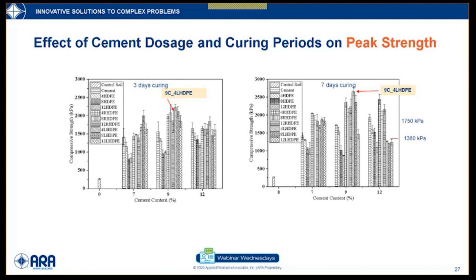This is to mention that these two red lines are indicating the minimum strength requirements according to the state and federal highway. It's showing that the minimum strength required for a rigid pavement subgrade layer is 1380 kPa, and for flexible pavement, the minimum strength for a subgrade is 1750 kPa. So the mix designs that go above this minimum strength criteria can be used as a subgrade mix design in the pavement.